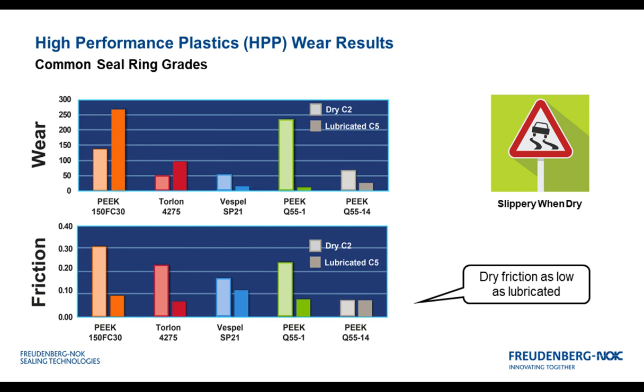There are PEEK grades. The green one has been traditionally used by us for many years for seal rings and other applications. And the gray one is a new material that we've recently developed. The bottom graph shows friction, and you can see the dry friction is typically much higher in these type of materials than the lubricated condition, where the lubrication becomes much lower friction and you don't see as much variation.